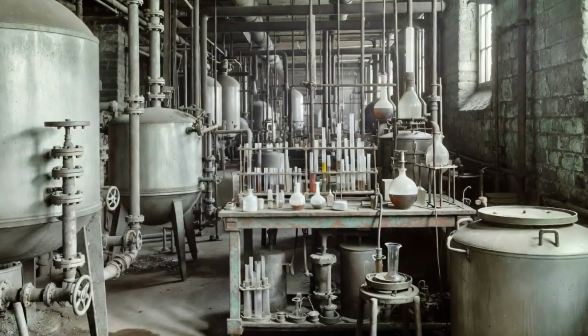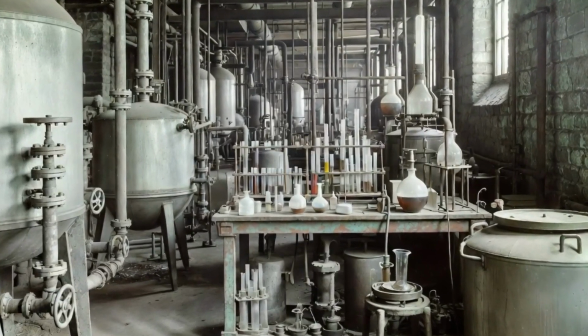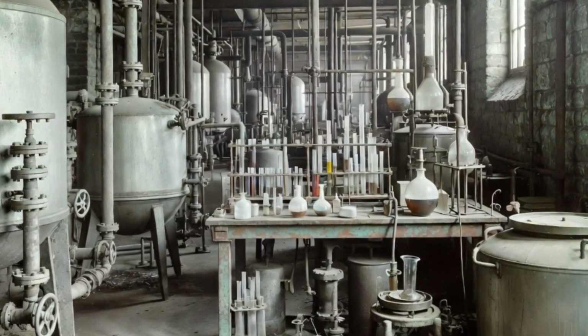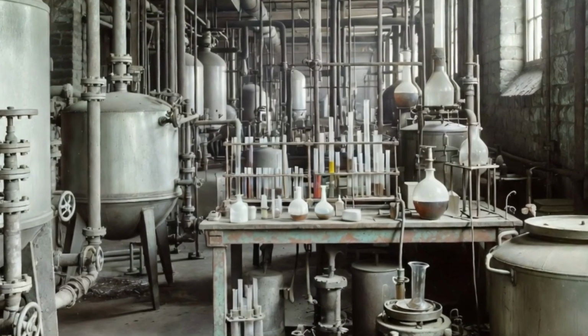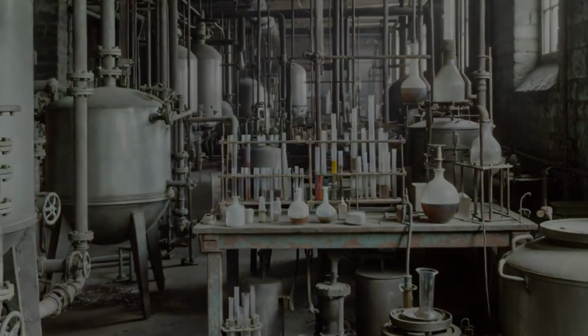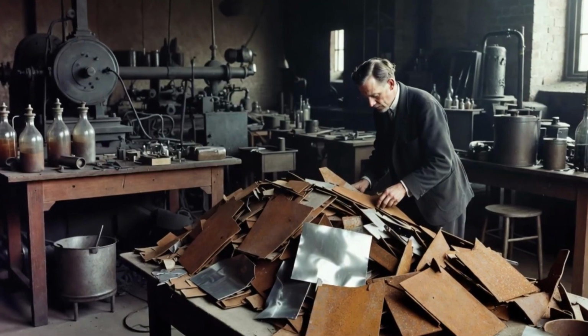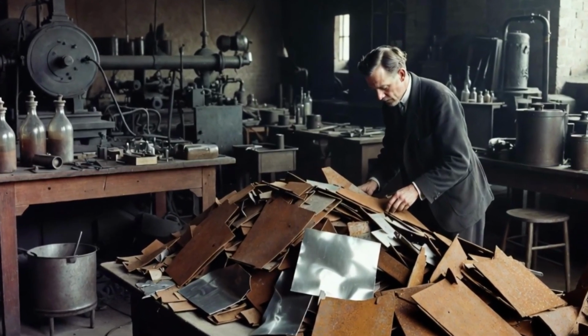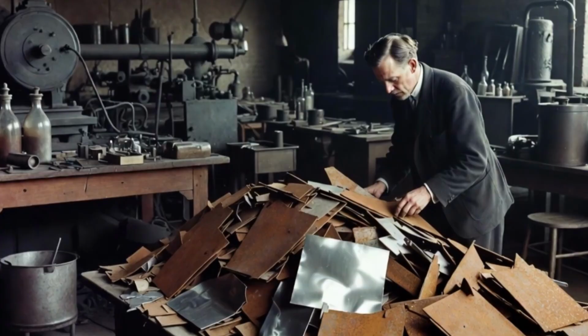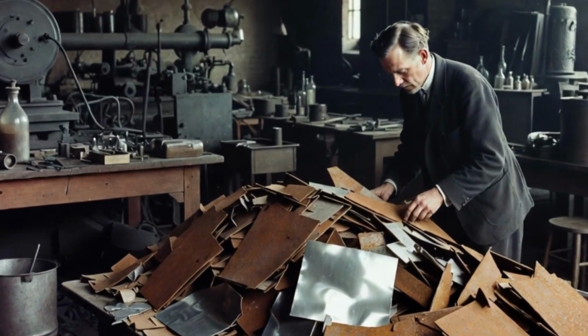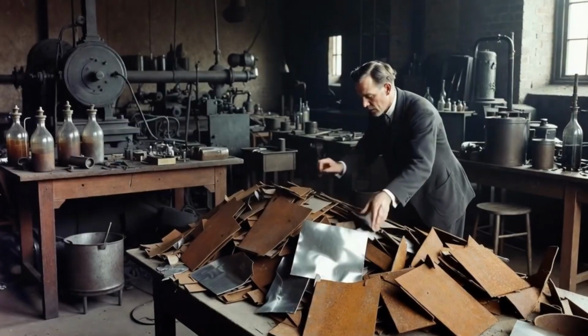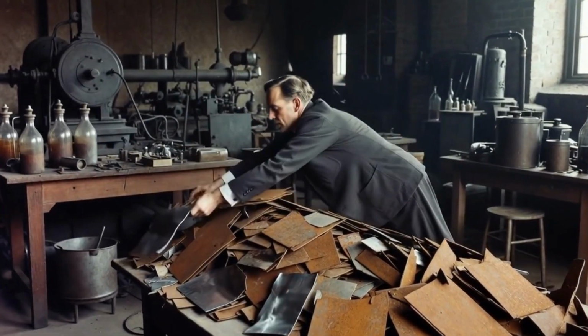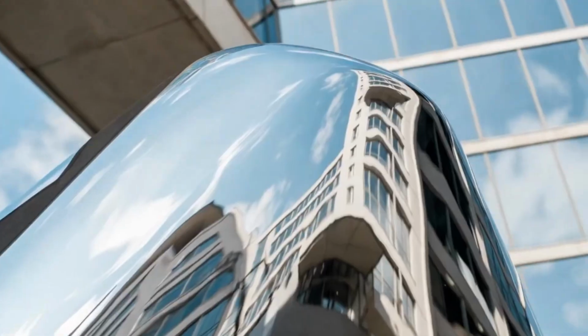Several months pass. One day he notices that most of the samples he set aside are covered in rust, but not all. A few, those with a chromium content above 10.5%, look like new, not a single spot of corrosion. Brearley begins analyzing, checking again and again. The result is reproducible. High chromium steel does not rust.